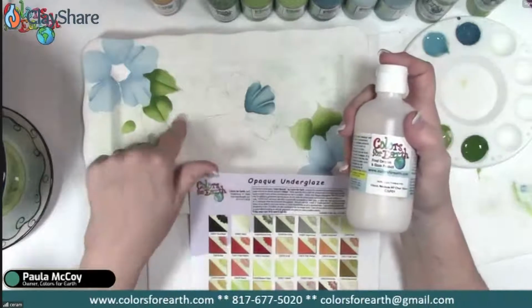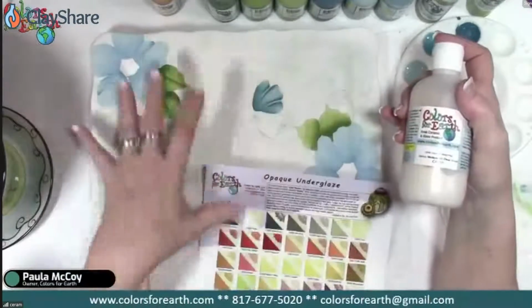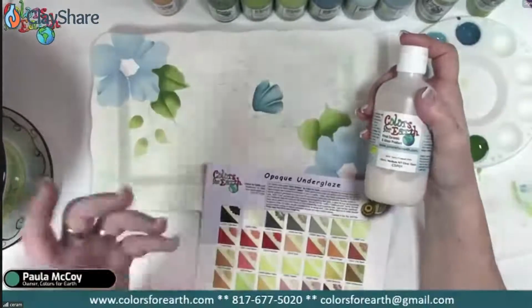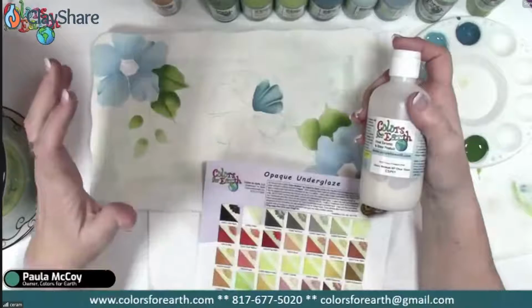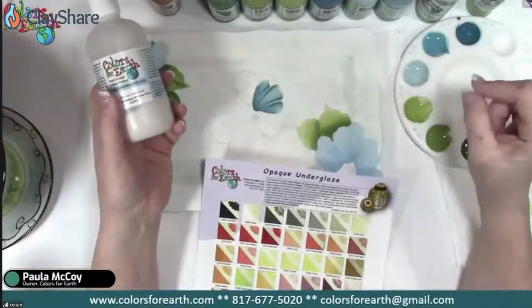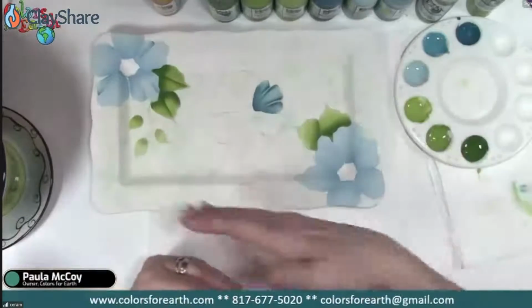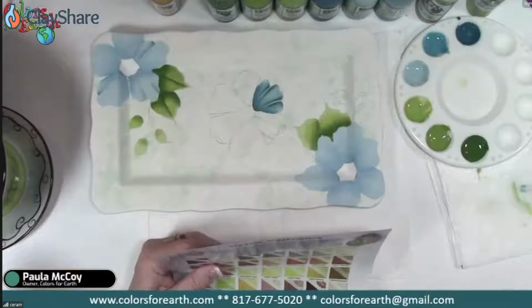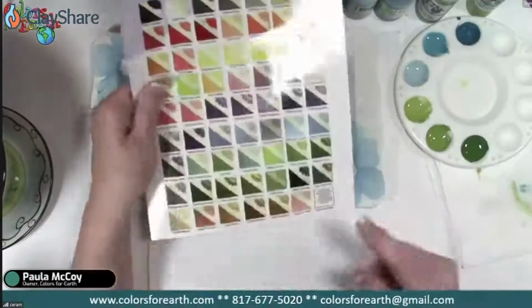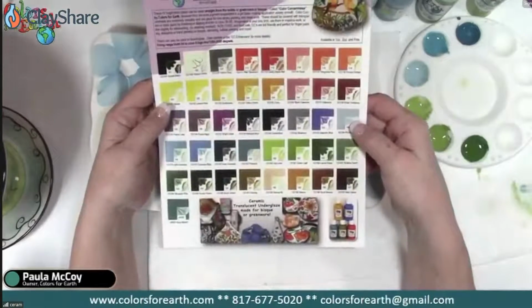So just like I did here. Just to clarify, if this was stoneware, I've got it on all my flowers and leaves, but I would put a stoneware clear glaze or Celadon or something that would complement it over the top of it. It's only for spot glazing is what I call that, spot glazing, because you're only doing different elements. You're not using it all over the same piece because it'll craze. I did it. I tested it. It crazes.